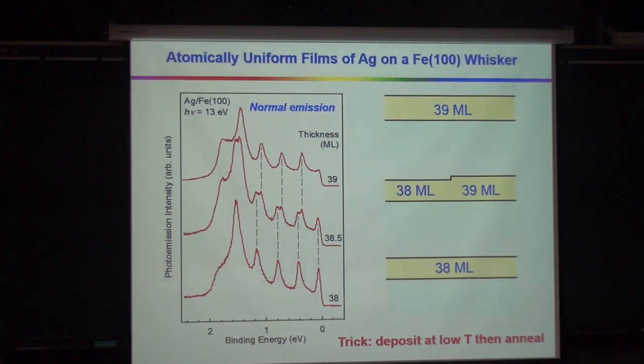So now let me show you, we can actually make these films quite well. So here we have silver on an iron (100) substrate, 38 atomic layers. And in normal emission, we see these discrete quantum well states, as I mentioned before. Okay, and then 39 layers, with another layer, and you can see these quantum well states are at different energy positions, because when you change the quantum well thickness, the energy shifts.